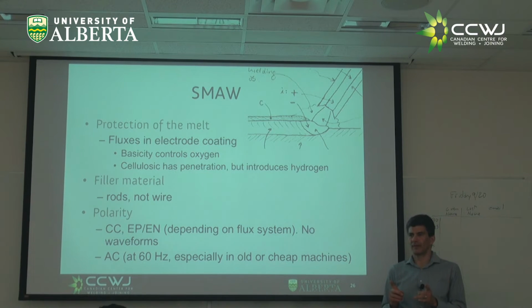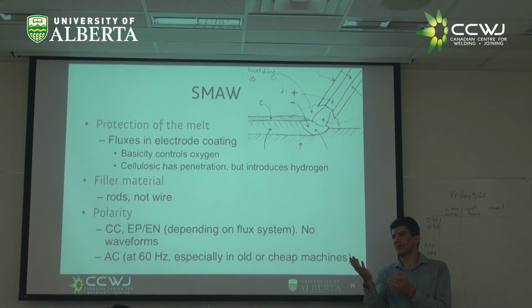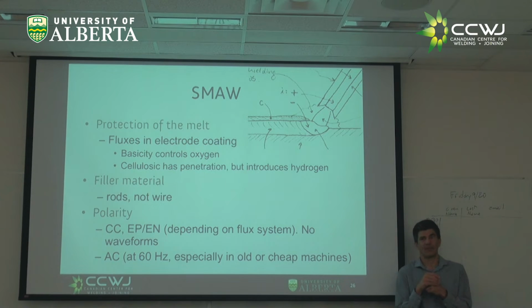When you do a root pass, remember the root pass with these cellulosic electrodes? You put so much metal in, and then after you did your weld for the root pass, you weighed it after. What is your efficiency? If you have, say, 10 pounds of metal, how much of that ends up in your weld? A number. I'm sure it's not going to be 100 because nothing is 100. Maybe 10? 45? Can be 0. I'll make it better. Can be negative. Actually, people have measured it's negative.